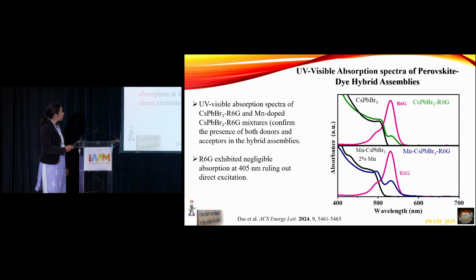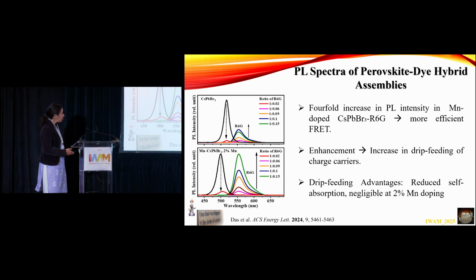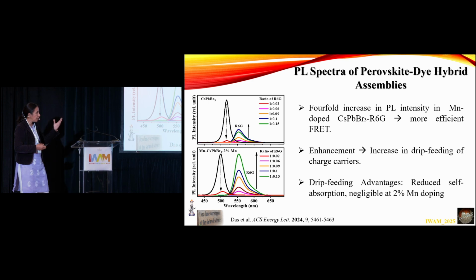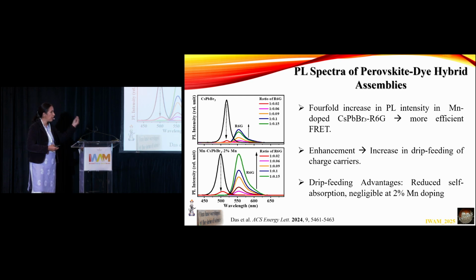We put in these systems, and very nicely we could see that as you go from cesium lead bromide to manganese doped cesium lead bromide, you could see almost a 4-fold increase in the PL intensity of the dye. And this enhancement is what we claim to be due to the increase in the drip feeding of the charge carriers. Another thing which came out as a relative surprise was because it's a drip feeding, meaning once you recombine, only then it gets this energy back. Although it is not Stokes shifted, we do not see self-absorption at very high intensity as well.